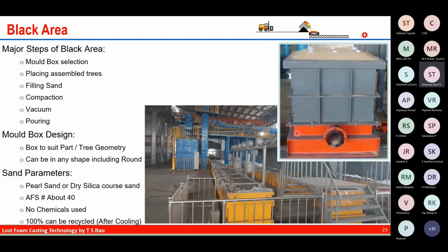Next, black area. Once the foams are made, getting assembled, coated, dried, and ready for metal pouring, comes to the black area. The major steps are like the mold box selection. We need to select the mold box which suits our part geometry. And we need to place the assembled trees into the mold box. We need to fill sand and we need to compact the mold box to ensure that the complete sand is packed. And we need to connect the vacuum and we need to pour liquid metal into the cavities.